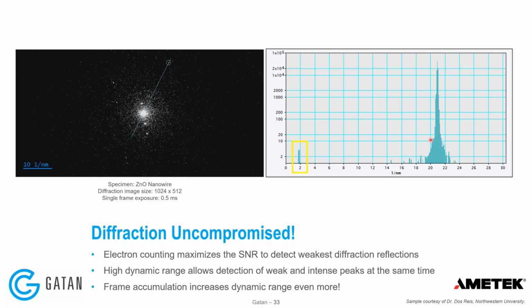I am not saturating the detector at the center beam. At the same time, because I am collecting data in electron counting mode, I am collecting signals from 1 or 2 electrons that result in 4 or 5 counts here in the image. So this is showing you both the advantage of electron counting, high signal to noise ratio diffraction imaging, and at the same time, the high dynamic range of the detector.